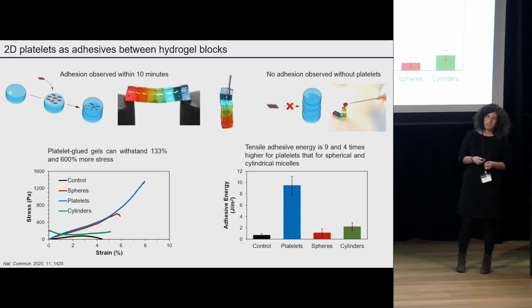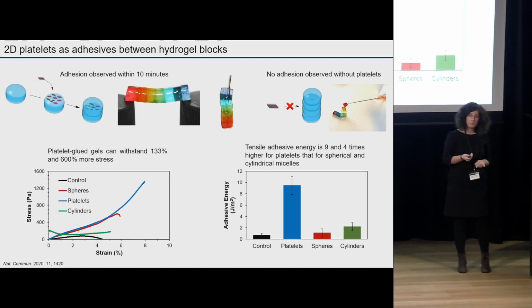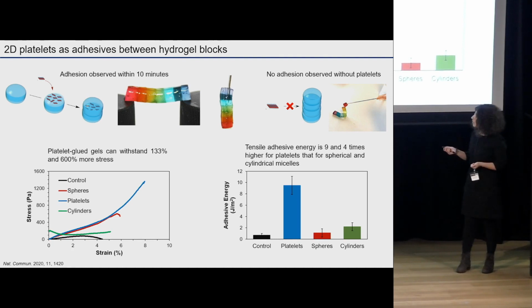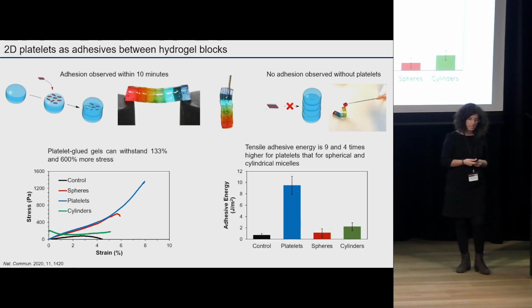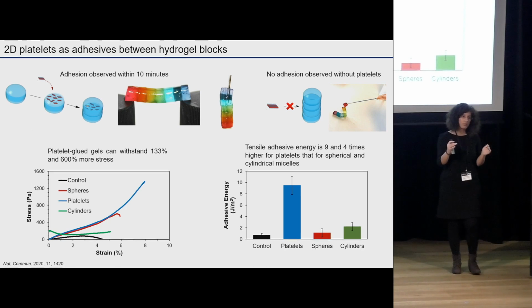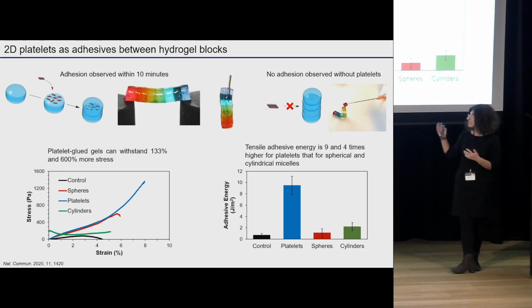And you can also pick up the material, and as you can see, the adhesion is actually quite stable. Obviously, no adhesion is observed if no nanoparticles are used. And what you can see in these graphs is that the 2D platelets have a much higher ability to adhere the hydrogel together compared to spherical and cylindrical nanoparticles. And we think that this is because they have a 2-dimensional structure. And so the 2-dimensional bits of the nanoparticles are allowed to interact better with the polymer at the top and at the bottom that they're in contact with, compared to any other nanoparticle that we tested.